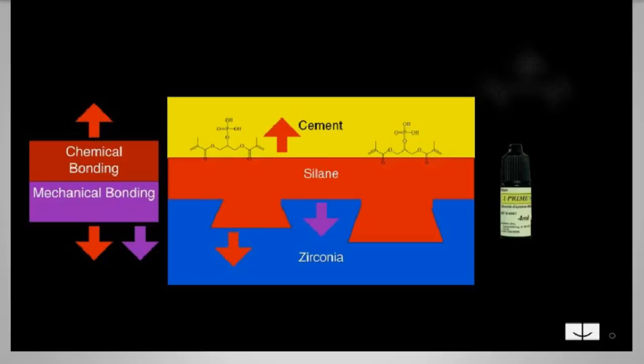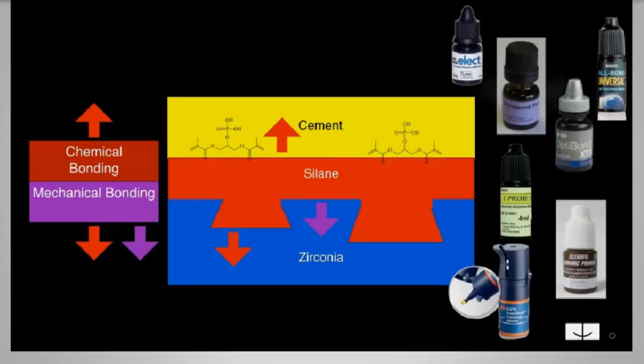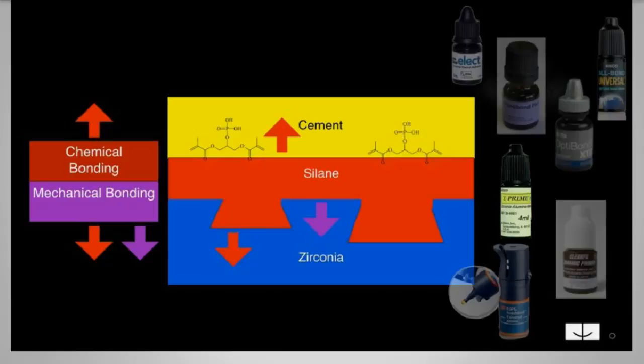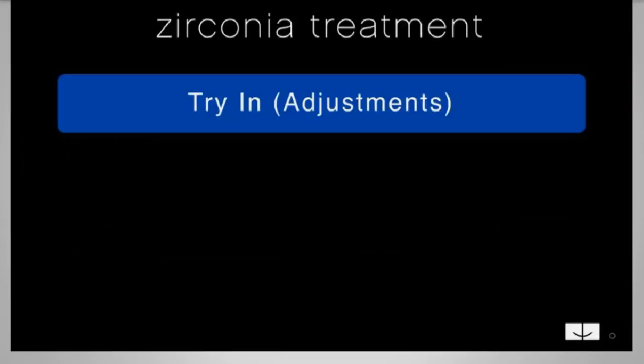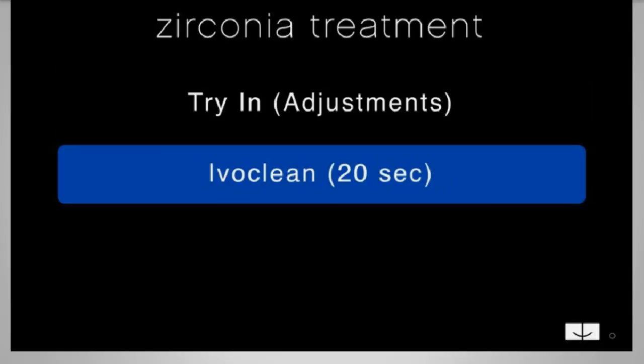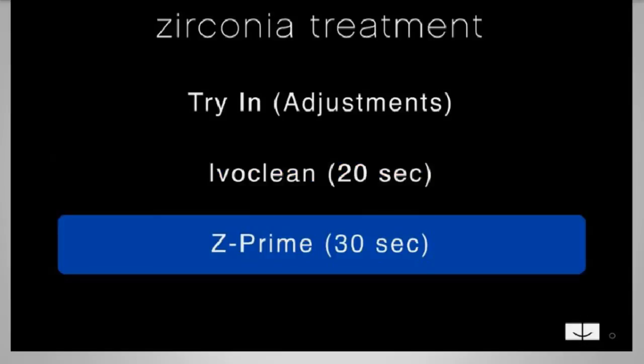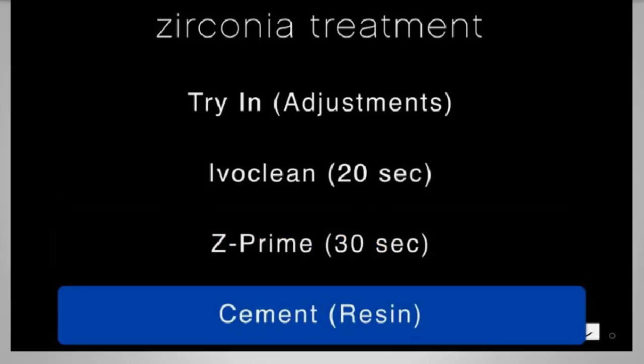And the zirconia primer works very, very well. Now, again, like I said before, lots of them out there. Lots of them claim you could do it. If it has MDP in it, okay, that's good, but the best is a zirconia-specific primer. Again, this is for non-retentive cementation. So this is how I treat my zirconia. Try it in, then I Ivoclean for 20 seconds. Then I put my primer back on for 30 seconds, zirconia specific. Then I can put my cement in.